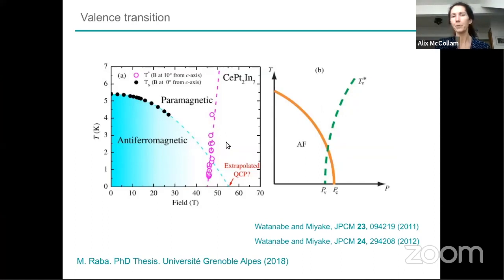And so we're proposing that this is a valence crossover. This is supported by theoretical work, and this is as a function of pressure here. The antiferromagnetism is suppressed, and a valence transition is also proposed and perhaps observed in ytterbium and cerium-based materials as a function of pressure in this way. In cerium metal also there is a valence transition, so it's known that this physics is happening in this system.